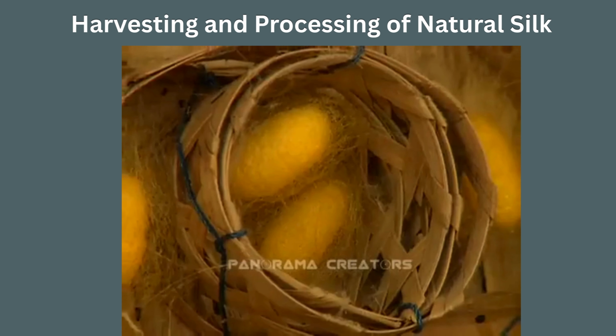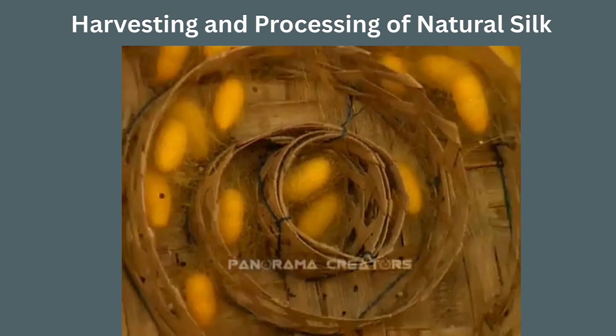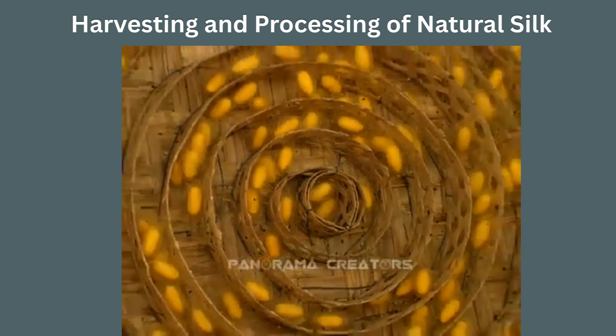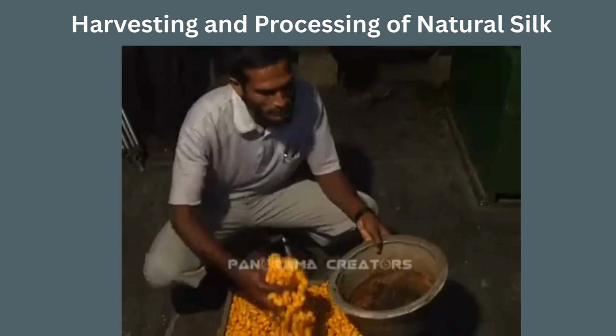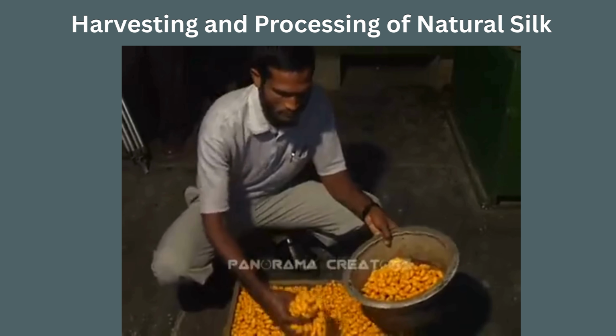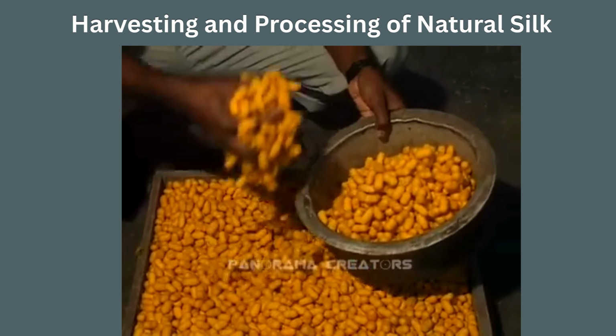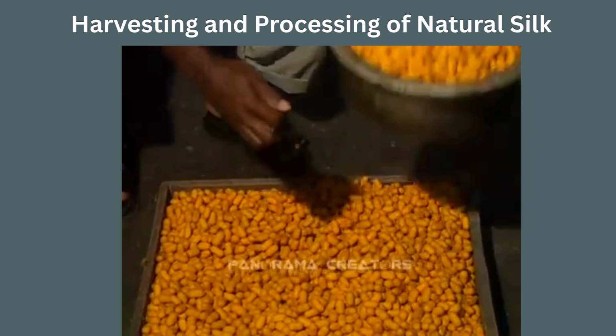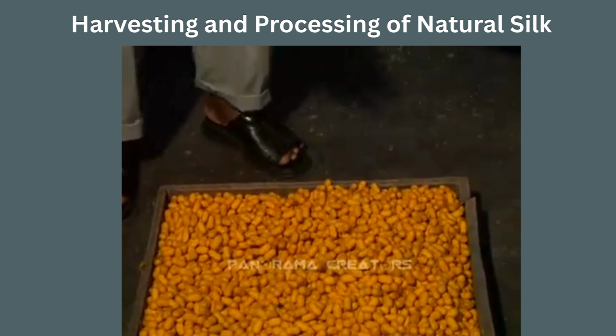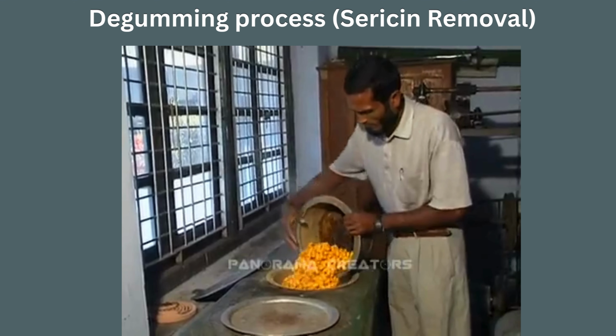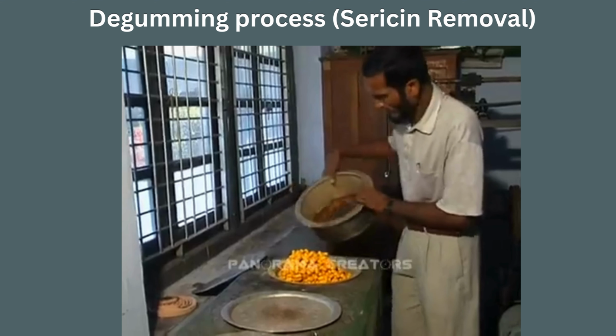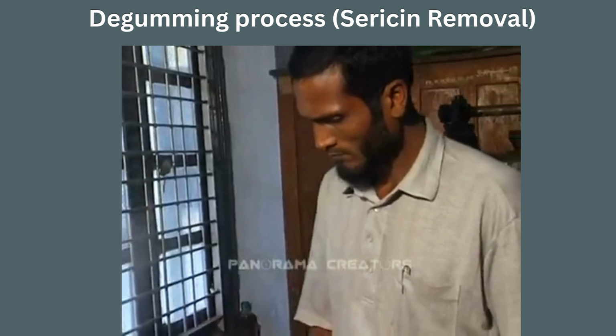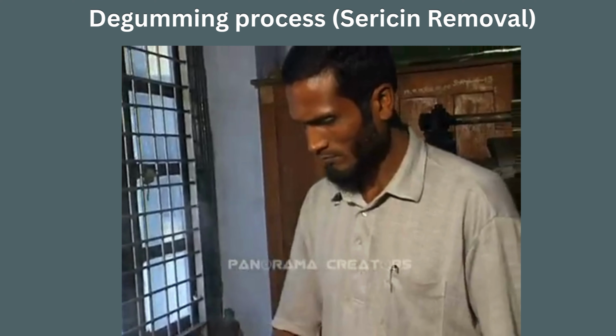Degumming process: sericin removal. Raw silk fibers are stiff due to the presence of sericin. Degumming is performed to isolate fibroin. Conventional method: boiling in sodium carbonate, Na2CO3, solution. Alternative methods: enzymatic treatment, microwave-assisted degumming. Proper control of degumming conditions is critical to preserve fibroin molecular weight and mechanical integrity.